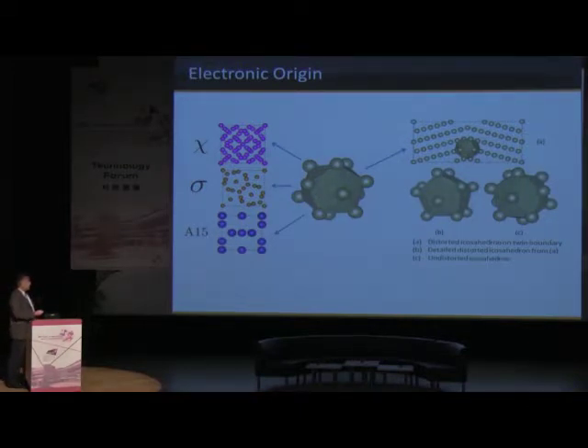And what we find is that in the twin boundary of rhenium, the atoms are surrounded by an environment which looks pretty much like an icosahedron. Okay, they don't at all look like the polyhedra that we have in the HCP crystal structure. Now, it turns out these polyhedra, these icosahedra, form in these other crystal structures, which are the so-called Frank-Kasper phases, which are shown over here.